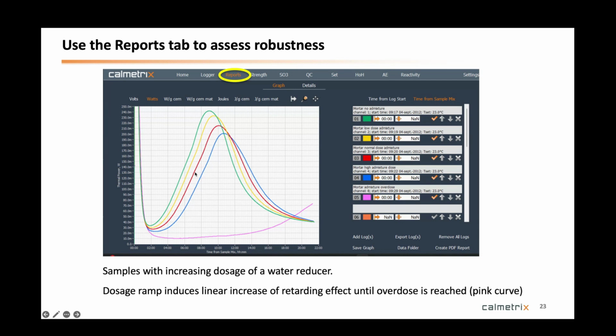So you can look at your robustness in a way: okay, if I'm off by 1%, how much does it affect the setting time in percent? And you can also see that at some point when you overdose, then you just kill the mix. That's the pink curve. So you can also find your limits. So here again, it's a very, very easy tool.